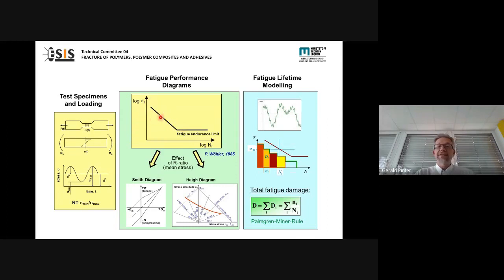So, and what you typically can find is such a curve, and sometimes for some materials you will even find a fatigue endurance limit. That is not the case for many polymers. So typically we do not find this fatigue endurance limit. And these Wöhler lines can be evaluated based on typical diagrams in fatigue, like Smith diagrams or Haigh diagrams, that typically also consider the R ratio effect. So the R ratio typically is the ratio between the minimum stress and the maximum stress in the test. So for these diagrams, a lot of tests at different R ratios, of course, are necessary.